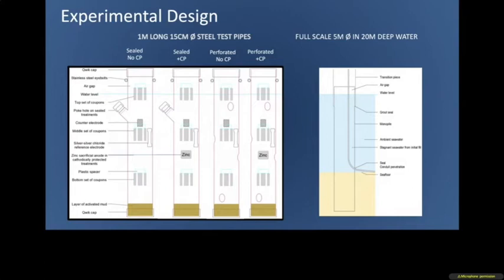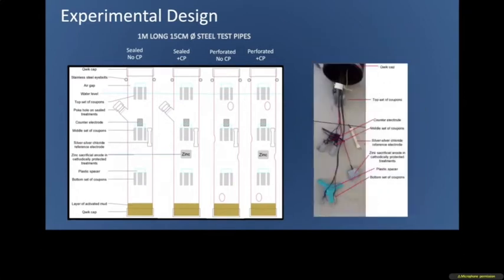And then we put in 2 structures which basically represented our concept of a perforated steel pipe, one with no cathodic protection and one with cathodic protection. And within these pipes, we put a small array of test samples. One of the things we needed in the cathodically protected pipes was a zinc anode. And then we put sets of test coupons at the top, center, and the bottom. And we also had the ability to monitor the potential and electrochemically interrogate the condition of the steel samples.